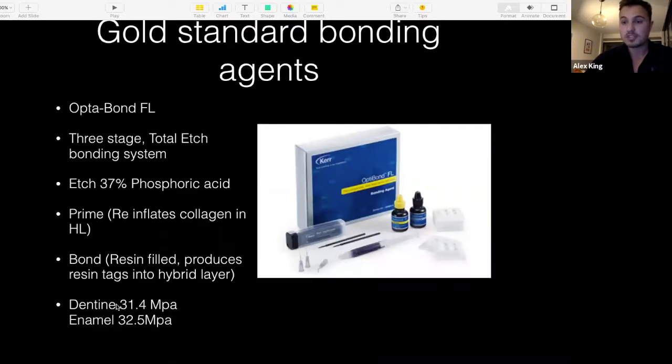And that is as strong as we're going to get. That's as strong as bonding to enamel, and enamel in good circumstances is 32. But there have been some in vitro studies of using bonding agents following all the principles we've discussed, deactivating MMP and removing caries, with actual dentine bonding strengths of up to 60 megapascals. So we should move away from the thought of adhesive restorations being just about bonding to enamel. If we can selectively bond to proper dentine using these bonding agents, we can get a much higher bond strength, and it's going to make our restorations last a lot longer, stay on a lot longer, and reduce sensitivity and protect the pulp's vitality.